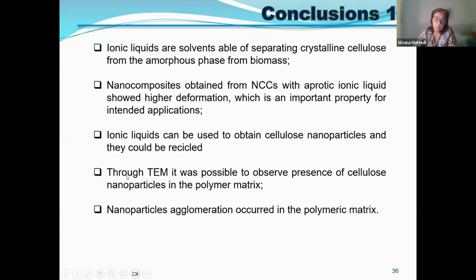Also, through the microscopy, it was observed the presence of nanoparticles in the polymer matrix, and they agglomerate in the polymeric matrix.